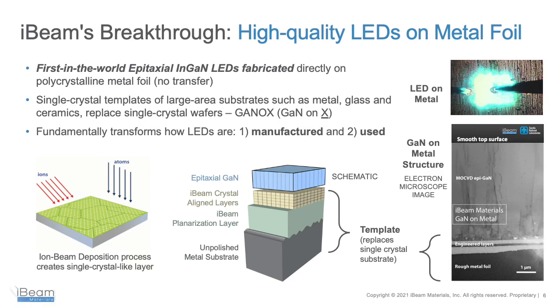In this case, we use the metal foil, but other substrates such as glass and ceramics can also be used. We call this process GANOX, where epitaxial GaN material is deposited on X, and X can be many different materials. For this, we utilize an ion beam process, shown here on the bottom left, where the ions orient a nanometer thin layer on the top of the substrate so that all the grains are aligned. The template shown schematically here in the middle then replaces the single crystal sapphire wafer.